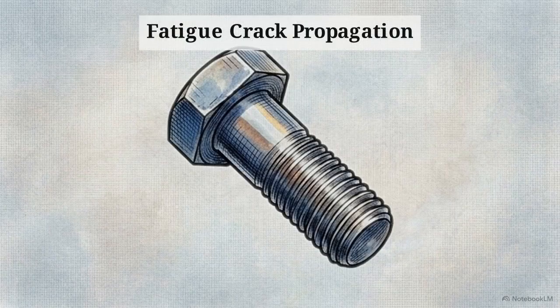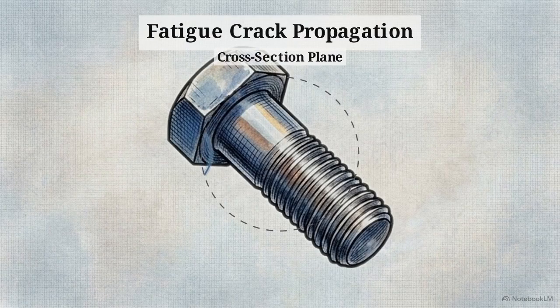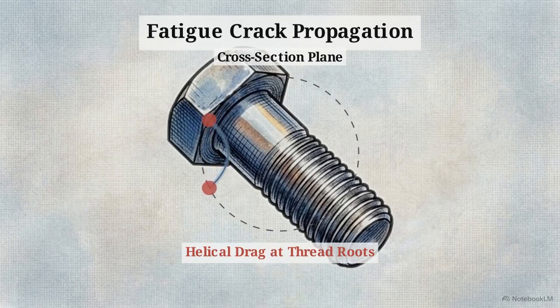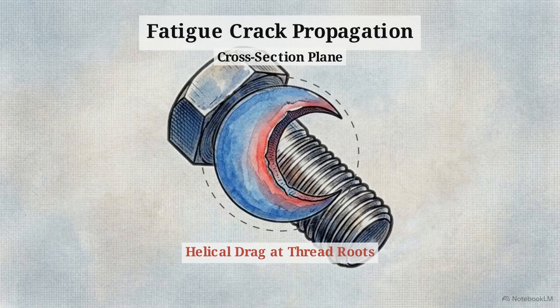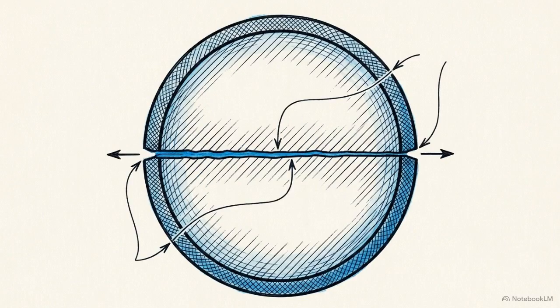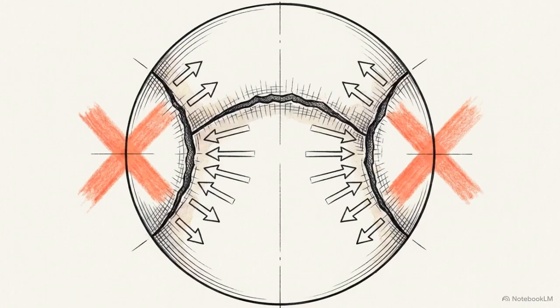This 3D model demonstrates the reality of thread architecture. As a flat crack propagates horizontally through the steel, its outer edges inevitably strike the spiraling thread root. Because a thread descends rather than forming a flat ring, the crack edges hit physical ridges, forcing them to drag and slow down while the center races ahead, bowing the plane into a deep curve. The crack front will remain flat only until its edges strike this geometric misalignment. The moment it hits the ridge, the local stress field shifts, and the fracture is forced to curve.